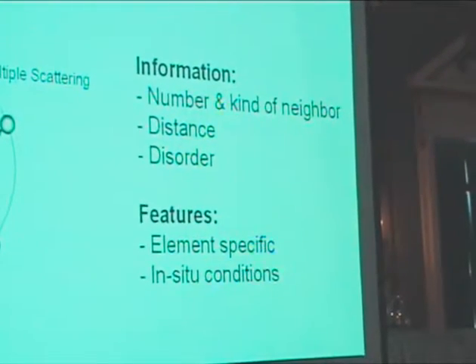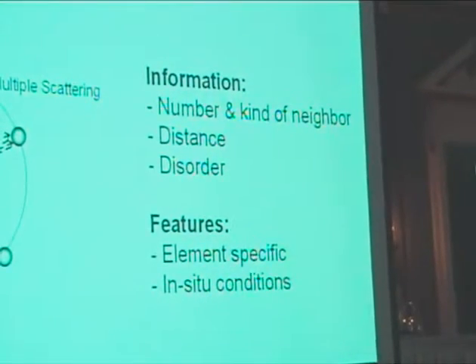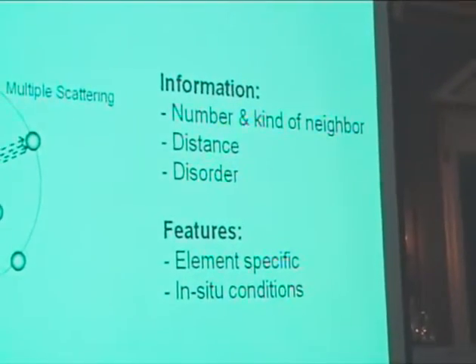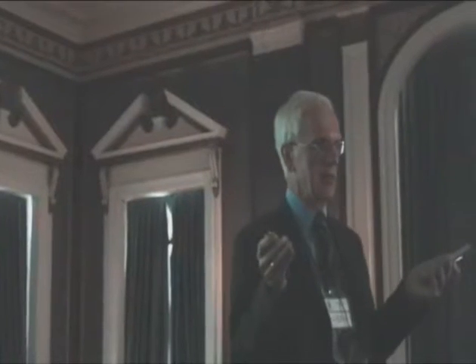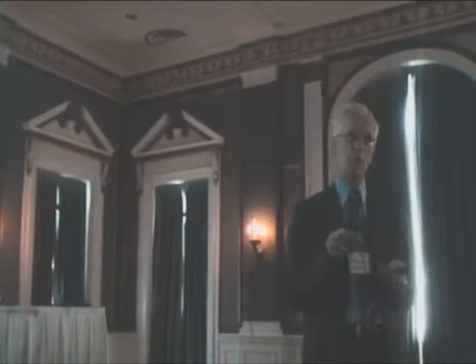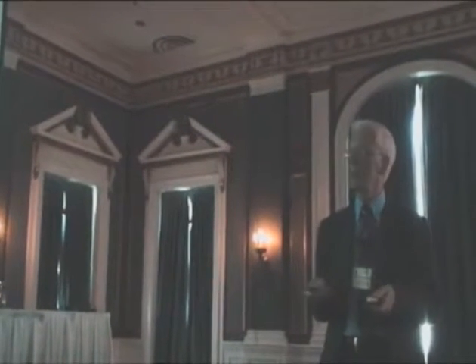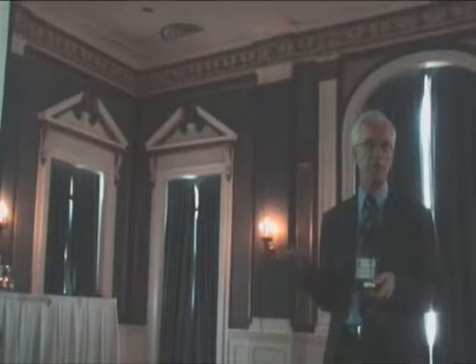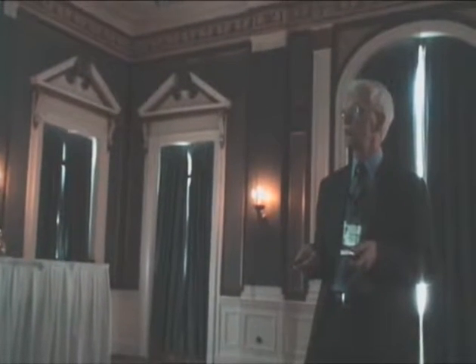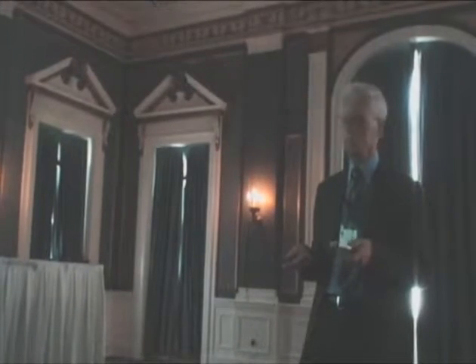You can do it under in situ conditions because we are talking about an X-ray technique. So you just have a chamber and you have windows, and you have quite a choice of materials for the windows, and the X-rays go through like they go through your body when you go to the hospital. And that makes the technique very nice for amorphous materials, and specifically here today for catalysis.